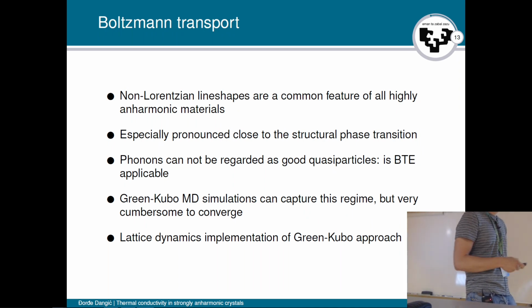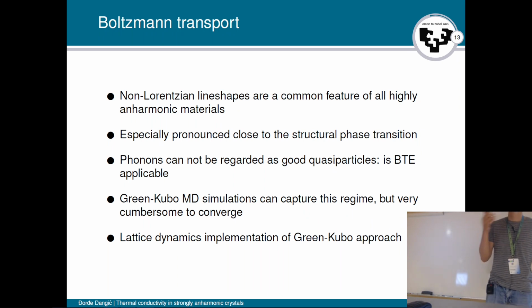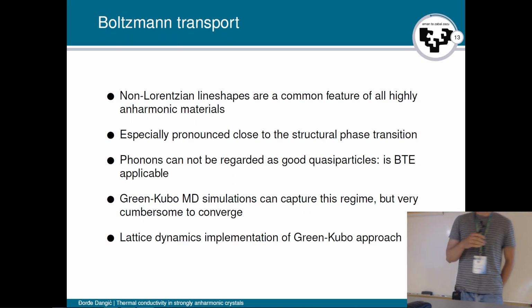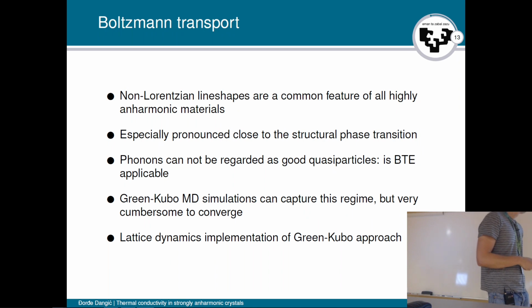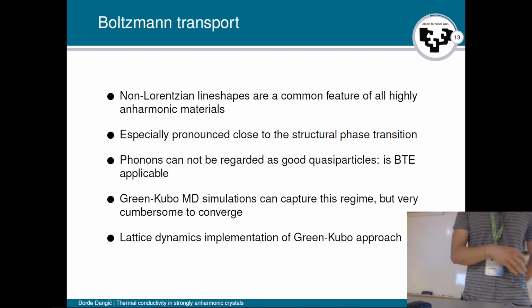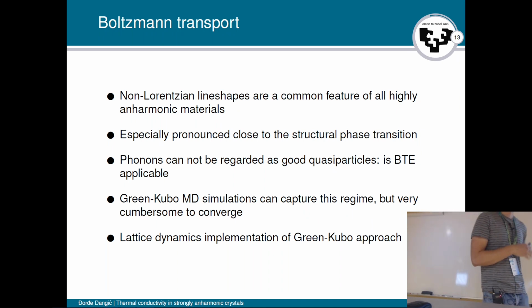So what we can do in this case is give up on the Boltzmann transport equation altogether and run Green-Kubo MD or direct MD simulations to actually calculate this. And this is a very good idea for a number of reasons. If we run Green-Kubo molecular dynamics simulations, we capture all orders of anharmonicity and all contributions to the heat current. So we don't make a lot of approximations when we do these calculations.